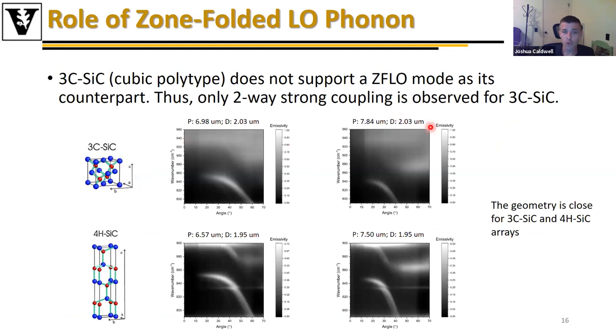Now, if I look at just pure 3C where these zone folded modes are not present, you can see I still can couple this grating mode to the monopole resonance, inducing this dispersion. However, the presence of the zone folded LO phonon actually provides some improvement in the actual quality of these modes and the total absorption of these resonances, in addition to providing an additional degree of freedom.